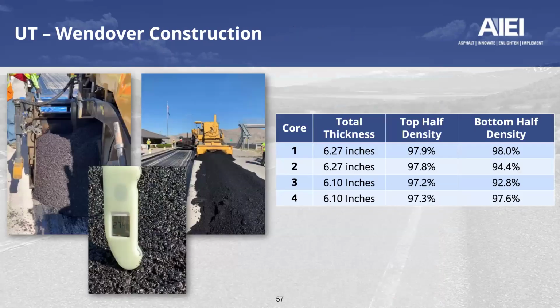And here's a couple of pictures from construction. Again, they're producing at about 300 degrees Fahrenheit, a 2-hour haul. The mix was losing about 25 degrees Fahrenheit when it reached the ground. Notice the incredible width of the windrow in front of that material transfer vehicle. And notice also the very fine densities that in general they achieved.